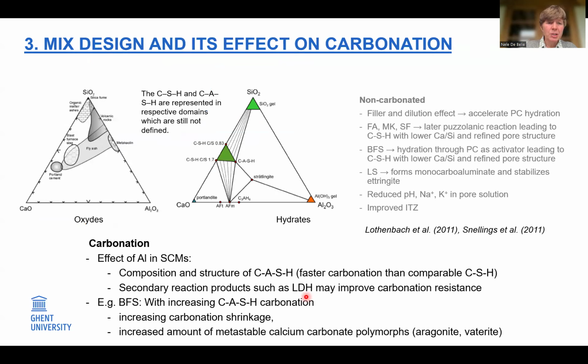For the phase assemblage, we can look to ternary diagrams. So here the regions are highlighted corresponding to the major SCM groups. And on the right, we can see the different hydrate phases. So this shows the broad range of compositions that can form as a function of the type of SCM that is used. The higher amount of alumina contained in SCMs will influence the composition of the CASH phases. And this has been found to lead to faster carbonation.